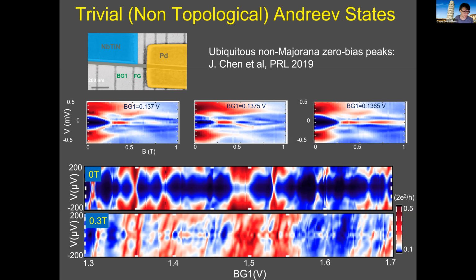They're very interesting. We have an upcoming paper that will hopefully be on arXiv soon. They're crossing the gap, but they're not sticking at the gap. Then when we apply a magnetic field of 0.3 Tesla, in the bottom panel, we have all kinds of regions where zero bias peaks form, seemingly independent of these crossing states. They just pop up everywhere.